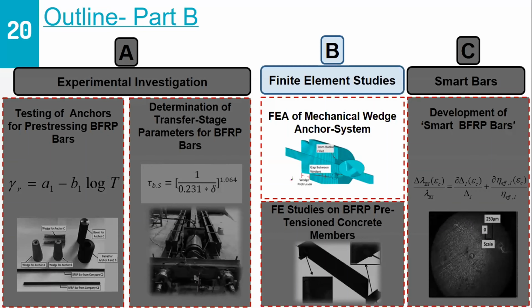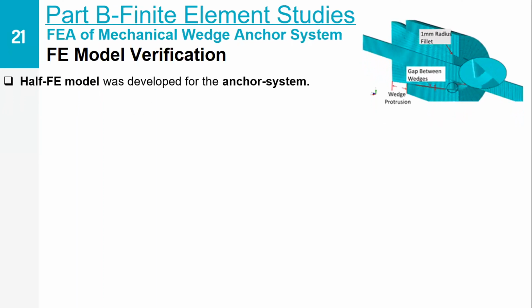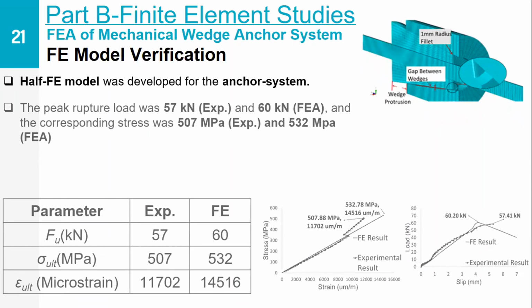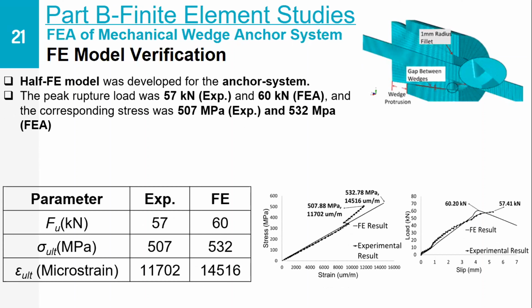Now coming to the next part, which is the finite element studies conducted as part of this research, first on the mechanical wedge anchor systems. So we have done some finite element modeling of this mechanical wedge anchors that we have tested at Queen's University, Belfast. And due to the symmetry of these anchors, only half model has been developed for these anchor systems. And we obtained a peak rupture load of 57 kilonewtons from the experimental results, and compared to that, the finite element result was quite close. So it gave a peak rupture load of 60 kilonewtons for these FRP bars.